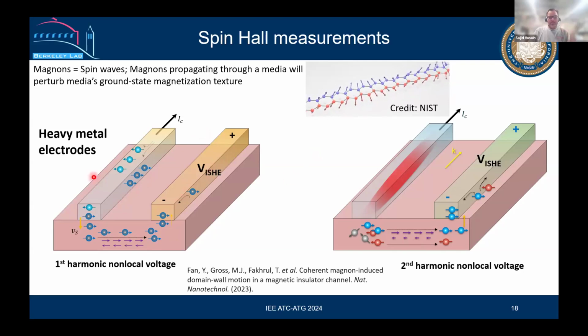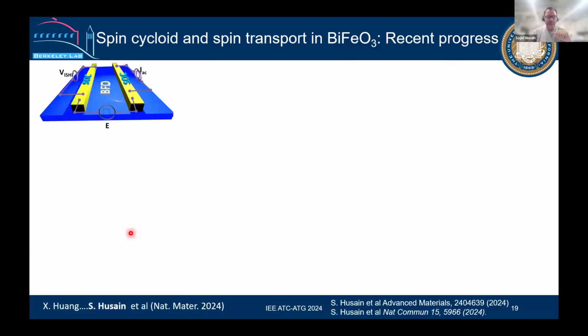The first is a first order effect, and the second is a second order effect. You are basically measuring the heat-excited magnons in the material. So I will bring up this word magnons in antiferromagnets. Because bismuth ferrite is an antiferromagnet, as I showed in my previous slide, the cycloid is an antiferromagnetic cycloid, but we can excite it through the spin Hall effect and through the heating effect, and we can measure the output voltage. And I'll show you how. The magnons are basically a coherent excitation, simple. I don't want to go into that.